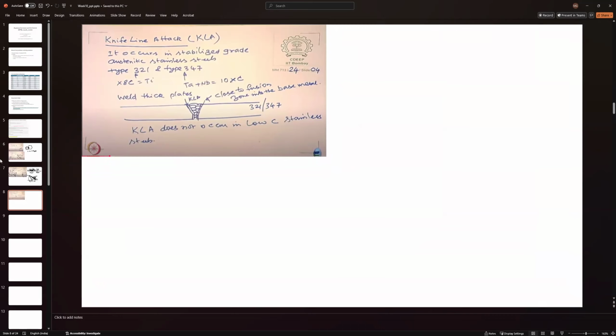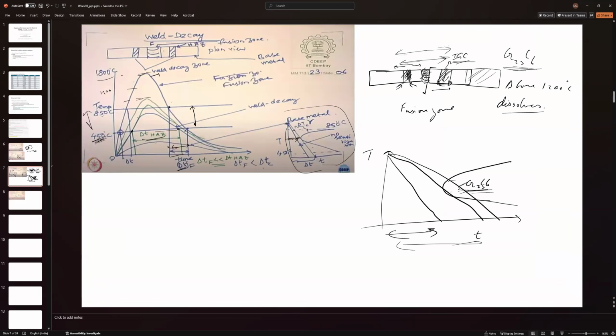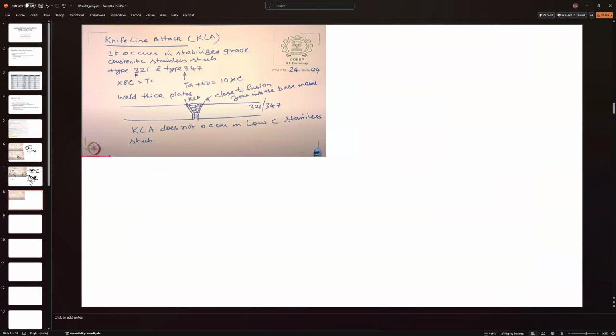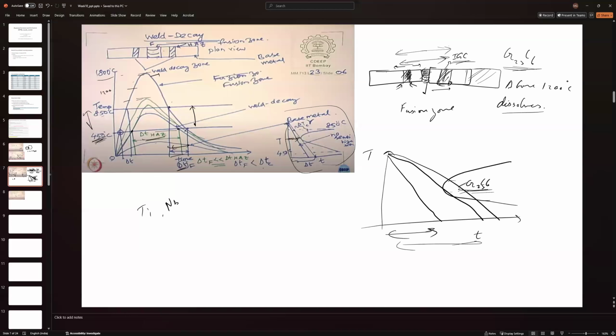What's happening? To prevent IGC, what you can do is add other carbide forming elements like titanium, tantalum or niobium, Nb. These will preferentially react with carbon, forming carbides and thus preventing chromium carbide formation. So the carbon is used up in titanium and niobium carbide precipitates, and you won't get chromium carbide precipitates. So this knife line attack happens only in the steels where you have some stabilizing elements. Tantalum, titanium, niobium, these are all stabilizing elements.